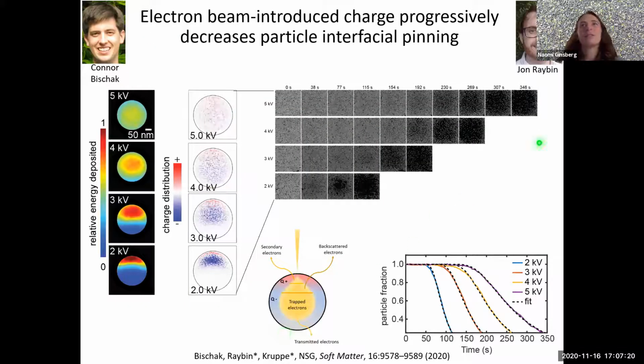And to explain these differences, Jon Raybin and Connor simulated the behavior of the dose of the accelerated electrons as the beam scans over the particle, showing that the net total charge on the particle and the average particle sinking time are correlated to one another. So at higher accelerating voltages, for example, at 5 keV, the beam fully penetrates the particle. The trapped electron charge and the positive holes that are left behind closer to the surface from scattering events in these insulating particles leads to a minimal net charge. But at lower accelerating voltages, the stopping distance in the particles really decreases a lot, and energy and charge are way more concentrated at the particle surface.